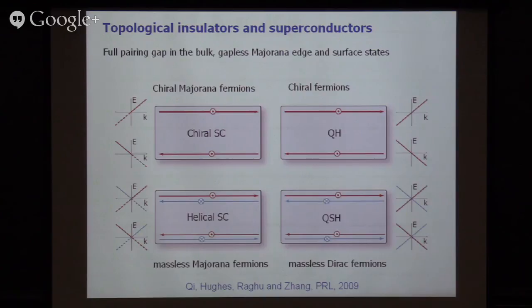And that's actually eliminated in a chiral superconductor. If you have a superconductor which is paired in p plus ip fashion, with L equals 1 and Lz also equals 1, then it has a full pairing gap in the bulk, but it actually has a gapless chiral state on the boundary. Now, because the superconductor is a linear superposition of particle and hole, this boundary state is not only chiral, it only has one particle type, and that's called a Majorana fermion. So this is called a chiral Majorana fermion on the boundary, and this is T breaking, but then there's also a T invariant counterpart. You can think of it as p plus ip for spin up and p minus ip for spin down.